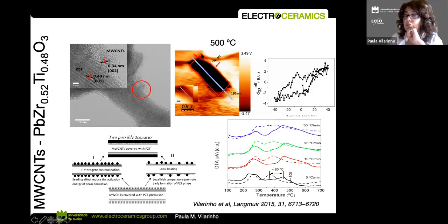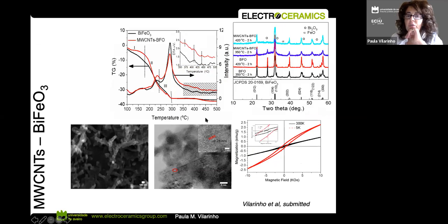So then what we did was really covering our carbon nanotubes with different types of materials like lead zirconate titanate and also barium titanate, and then treat them and then measure the properties. And this was quite interesting. As you can see here, this is the structure of our carbon nanotube, and then we have something on the top. And then what we are measuring is indeed properties that were not able to be measured before. And this is not easy, I would say, covering the tubes exactly as we want and how we want. It's not an easy task, but I think it's feasible.